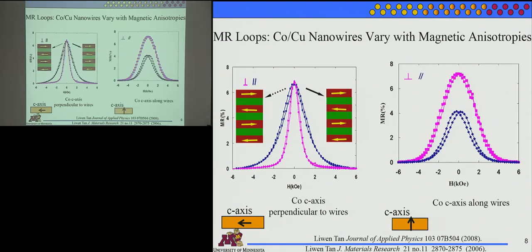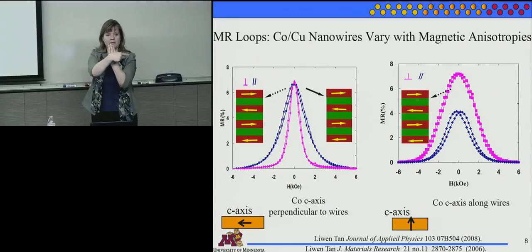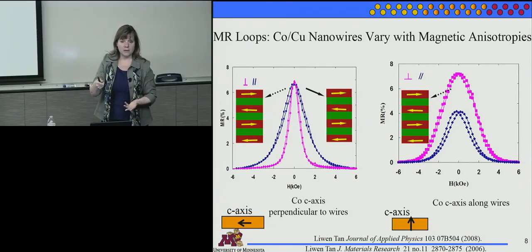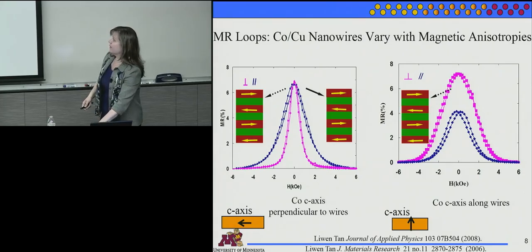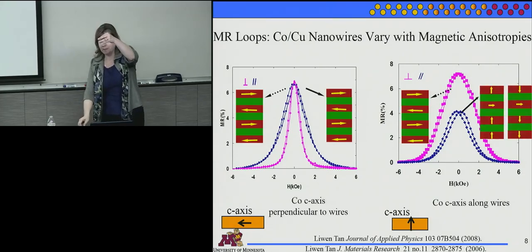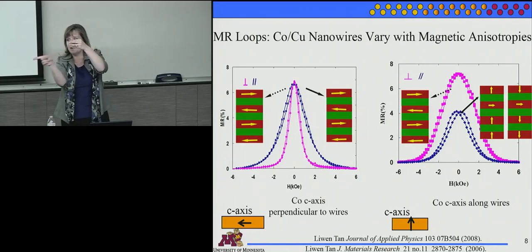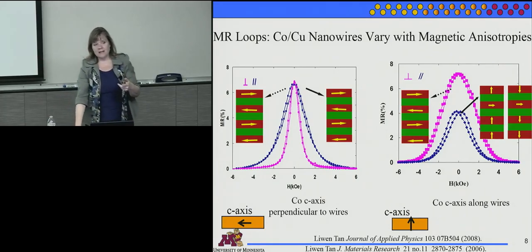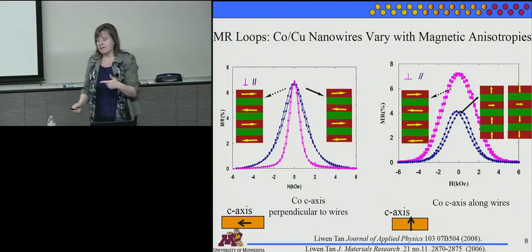So what happens if I change the anisotropy? So here I have a c-axis that's perpendicular to the shape. The shape is still a pancake, but the c-axis is perpendicular to that. And now what you find is if you orient the same way, go ahead and have all your wires lined up and apply the field, take it away, apply the field backward, forward, you still get a very similar shape to the curve. But if I go and tilt my wires this way and magnetize them parallel, well, one of the easy axes is actually along that axis now.